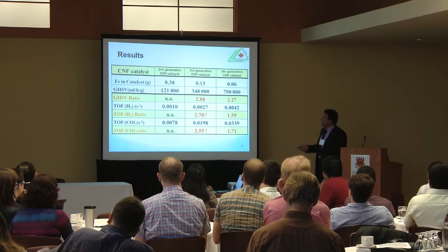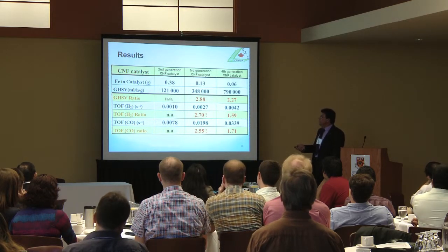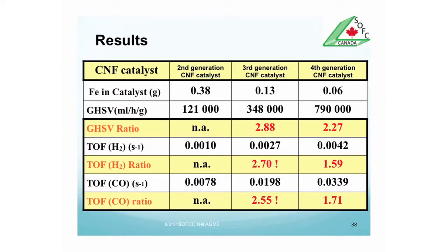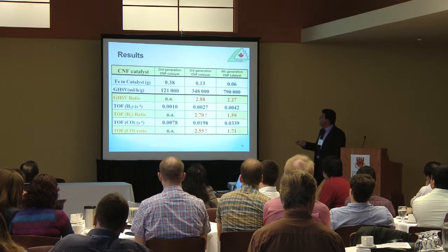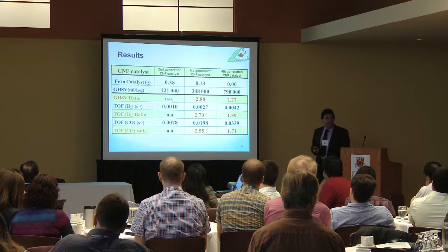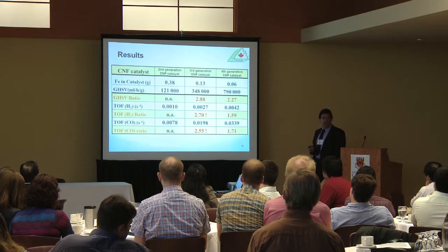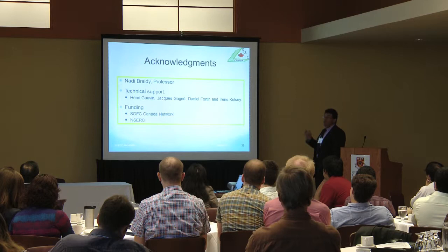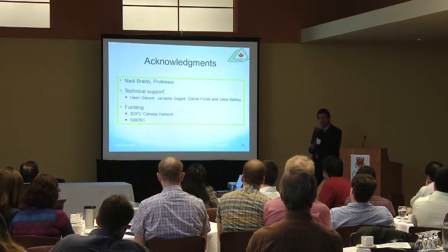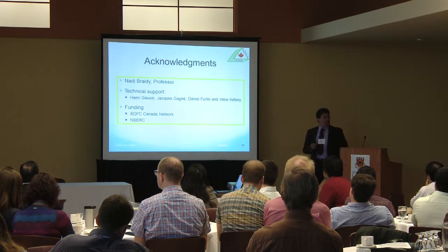Then if we get data on turnover frequencies, which essentially is the means of obtaining the efficiency of the catalyst for the production of hydrogen and the production of CO, we see that as we move forward to the next generation catalyst, the turnover frequency increases. This is something we didn't really explain yet, but perhaps it's a question of availability of the iron carbides, which is higher due to higher surface. So I will stop here. I'm within time, I suppose.